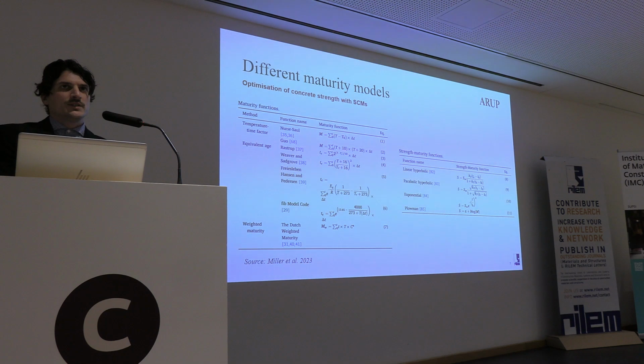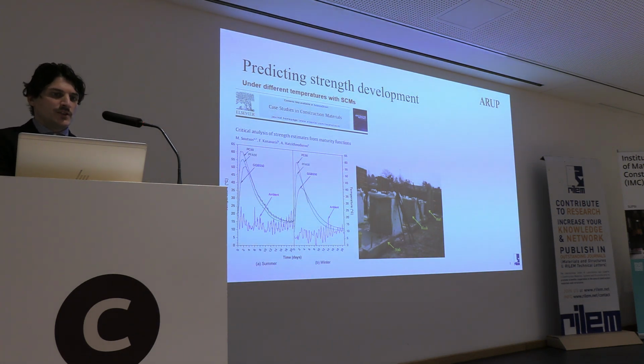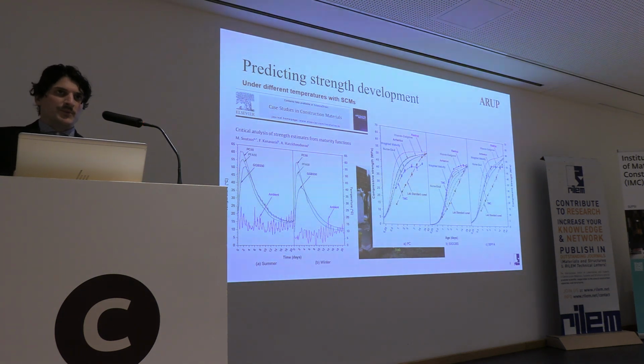So we said, okay, we have to review all these models and understand their deficiencies and how these could affect prediction reliability in terms of strength, but also in terms of other properties as well. So through a series of studies, particularly for concrete containing supplementary cementitious materials, we investigated different curing regimes, different non-isothermal conditions for concretes with SCMs. In particular, this was taken from a mock-up study including blocks, walls, and slabs, and we were able to develop this kind of modeling analysis with a maturity function for predicting strength, and actually pointing to what the deficiencies are. And the deficiencies are important because they hinder the further application of this approach in understanding the evolution of concrete properties. So there are different models that could be applied to different concretes with supplementary cementitious materials, but there is increased variability.